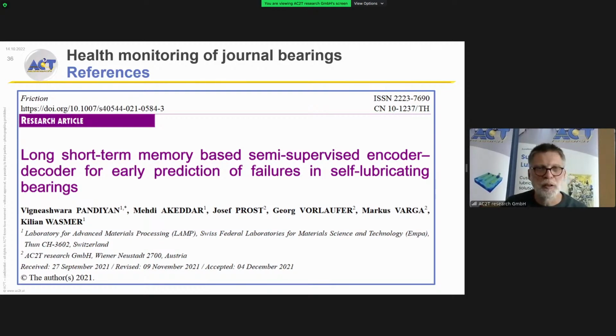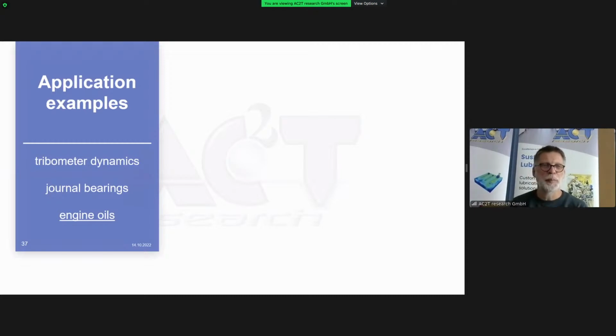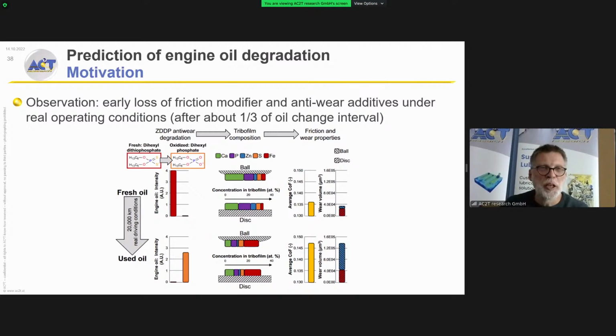Okay, and now since I'm running out of time, I go to the third example, which I have prepared. This now deals with engine oils, and the methods here are more on the classical statistical side. Again, starting with a motivation: what our colleagues from our chemistry or lubrication group observed in long years of collecting data in field tests in passenger cars is that about 1/3 before the envisaged oil change interval, the modifiers in the engine oil, which would reduce friction and prevent wear, start to degrade or start to disappear.